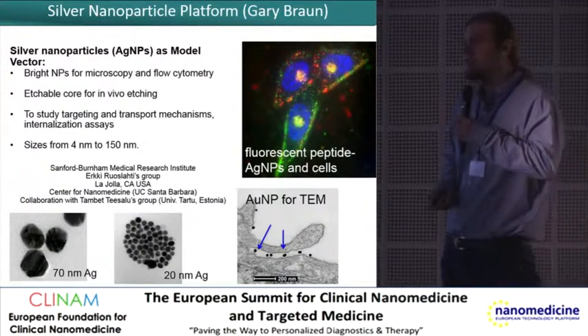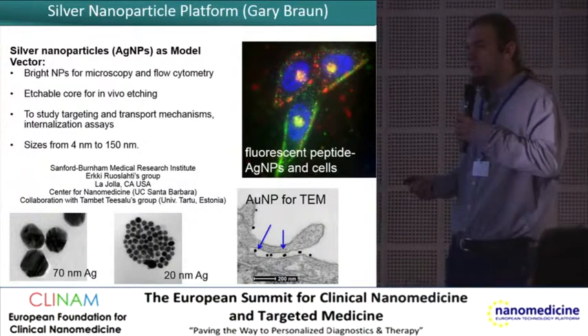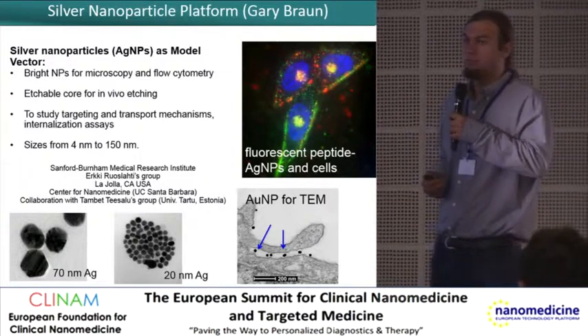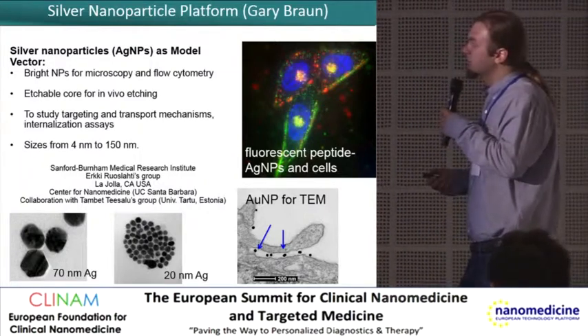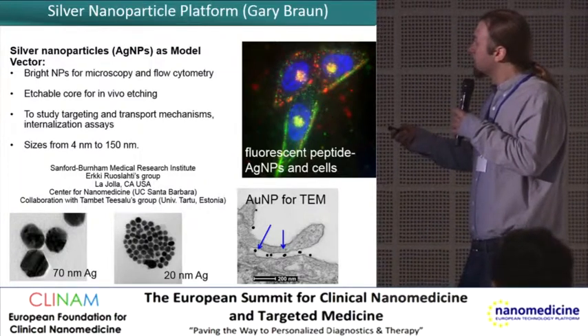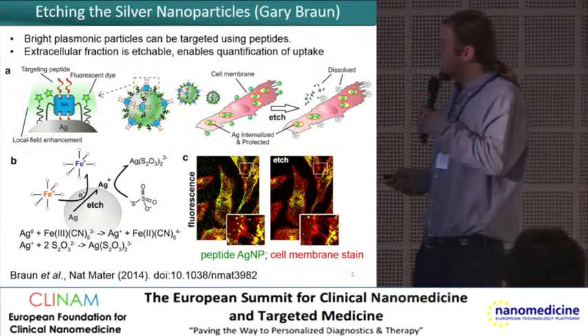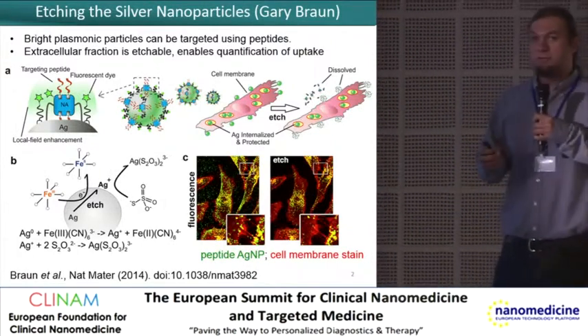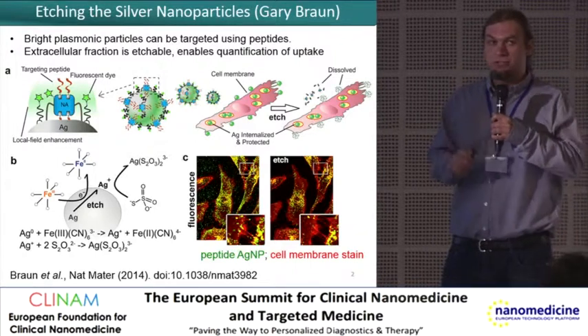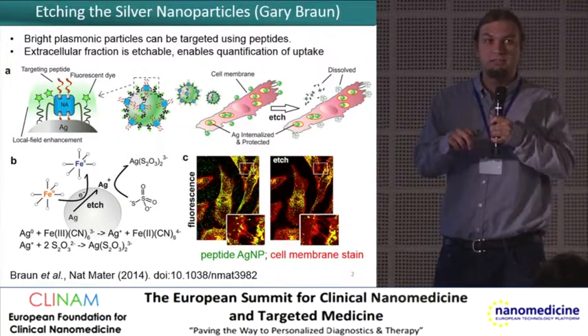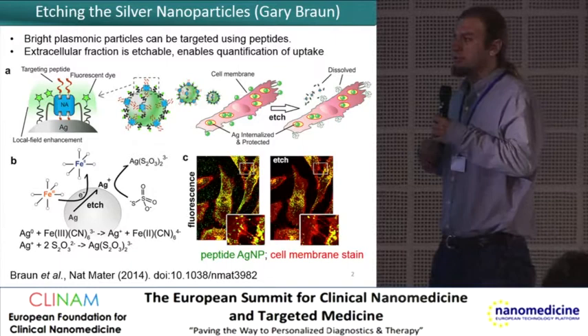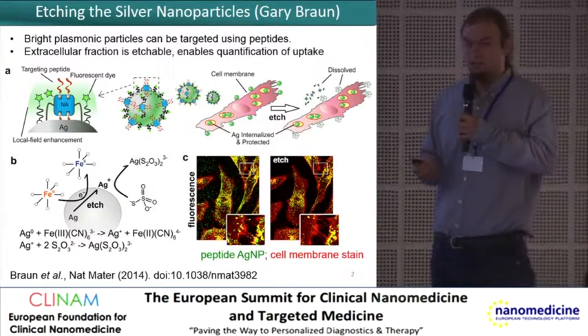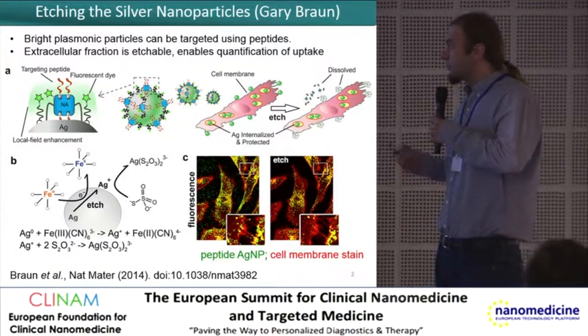The size can be controlled, so we anticipate a study of size-dependent internalization. The peptide density on the surface should also be important for receptor-mediated endocytosis. The system we developed is an etching process that allows discrimination between internalized and non-internalized particles, so we can image and quantify the amount of particles that entered the cells.